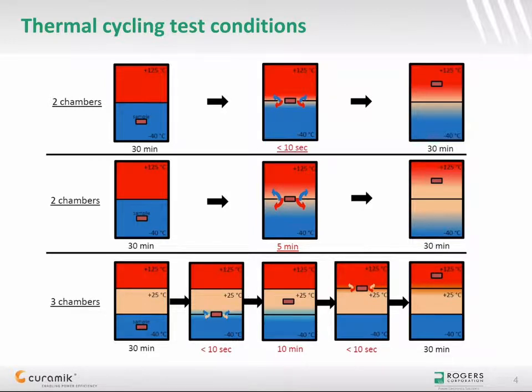Third, the minimum and maximum temperature, as well as the temperature difference between min and max values, can vary from one manufacturer to the other. In most cases, substrates will be tested between minus 40 degrees C and plus 125 degrees C, but one can find minus 55 degrees C up to 150 degrees C as recommended in some norms for military applications.